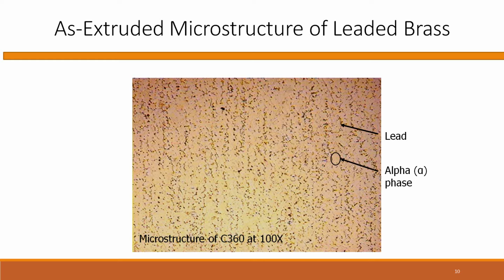And the consequence of the lead distribution and the copper and zinc ratio and the hardness and the cold work is the most machinable alloy of any kind of form, whether it's a leaded steel or a sulfurized steel or aluminum alloys with lead or whatever else they might use in there. Everything is measured against alloy 360 in terms of machinability, where alloy 360 is rated at 100%. And as you get away from using lead and go toward using alternative materials or approaches, you have to do whatever it takes to get the machinability as high as possible.